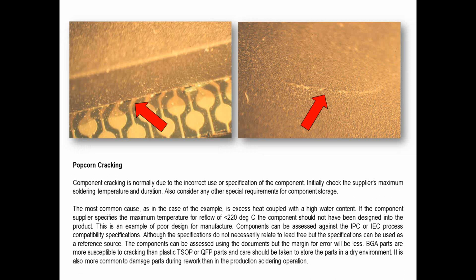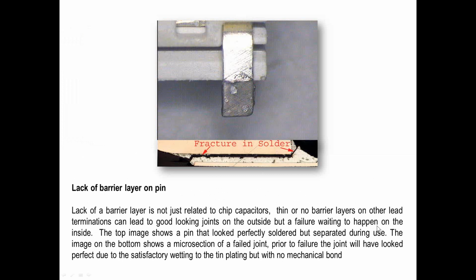However, if you're going to be reworking product that's coming back from the field, or product that's been on the shop floor for a period of time, which hasn't had the same control that the components would have had in their original packaging, then you need to pre-bake to make sure you're not introducing a problem at a later stage. And popcorning is a well-found term for this defect, because if you are reworking and you stand very, very close and be very quiet around a component being reworked, you can actually hear it pop. Trust me, I'm a consultant.